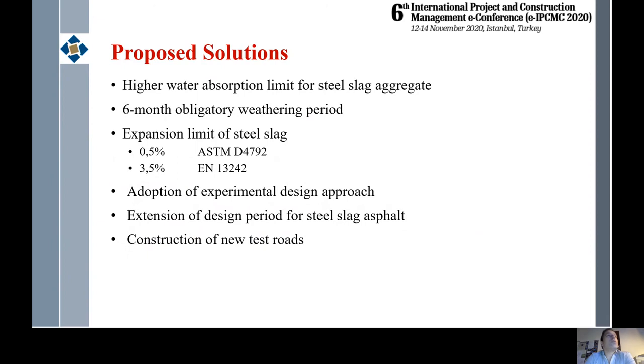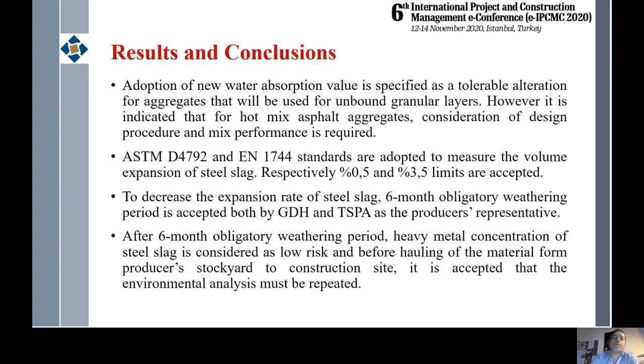And according to these drawbacks, we have some solutions that are proposed to the General Directorate of Highways and also the Turkish Steel Producers Association. A higher water absorption limit should be specified for steel slag aggregate. A 6-month obligatory weathering period. Expansion limit of steel slag is presented as 0.5% and 3.5% for different standards. Adoption of the experimental design approach, extension of the design period for steel slag asphalt, and construction of new test roads.